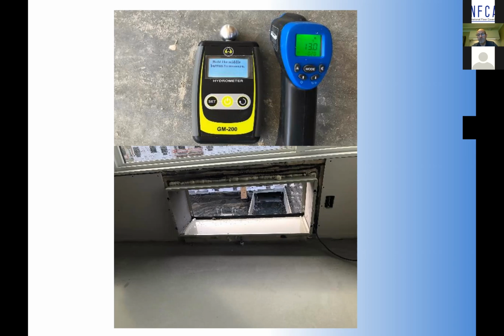Because if we're trying to install a floor at 13 Celsius, that's 55 Fahrenheit, and material gets very stiff and very brittle at those temperatures. It doesn't contour with the substrate as well, it doesn't lay as flat, it doesn't seam nicely, and it doesn't react properly to heat welding. So at the preparation stage we have some flexibility to go a little bit lower, but for the actual flooring installation, it's very critical that we have proper site temperatures.